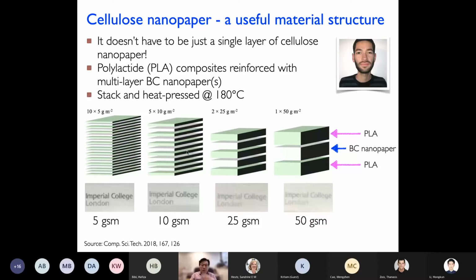Or you get 5 sheets of 10 grams per square meter, which then also gives 50 grams per square meter in the final composite, or 10 sheets of 5 grams per square meter nanopaper stacked up together. So overall, you have 50 grams per square meter of cellulose nanopaper laminated with polylactic acid as the polymer matrix. And in this case, the way you manufacture them is to stack and you press, as simple as that.